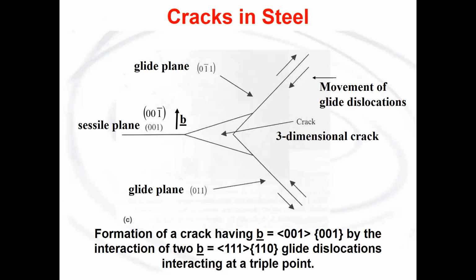One interesting thing to apply this to in the future would be to look at how cracks are formed. An example here is a crack forming in steel, where you have the movement of glide dislocations from 2 planes intersecting with each other to form sessile dislocations. And when they build up, they actually form a 3-dimensional crack. So this has never been seen before. So I think this method will allow this mechanism to be studied.